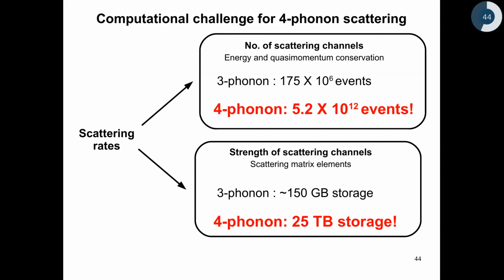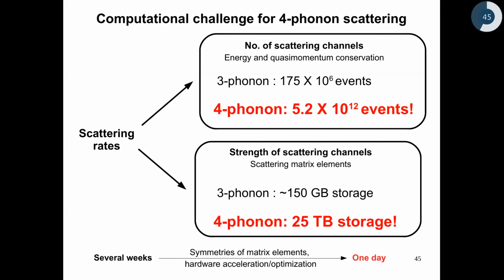But if you look at the corresponding numbers for 4 phonon scattering, the number of allowed events go up by 4 orders of magnitude, and the corresponding storage also increases significantly. So when I first implemented this code, the first version actually took me several weeks to get a converged thermal conductivity number. But over the past couple of years, I have implemented several symmetries of the matrix elements involved in the scattering rates, scattering strength calculations, and also incorporated several hardware acceleration features to bring down the computational cost and the computational time to an order of 1 day.